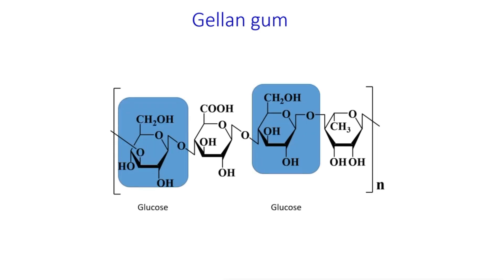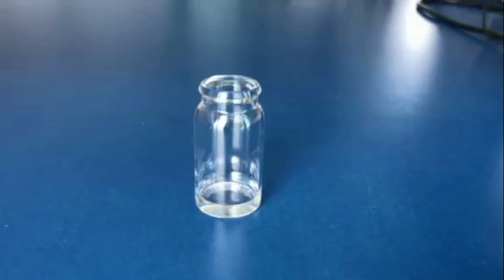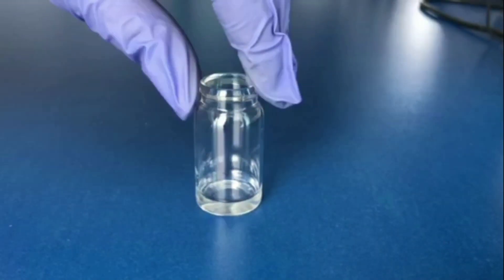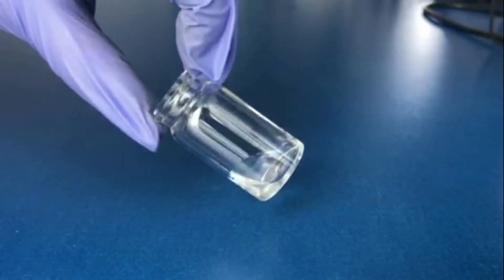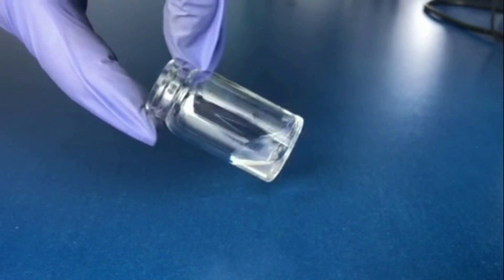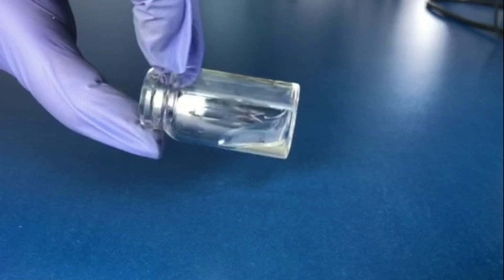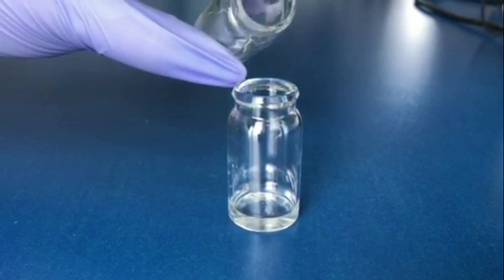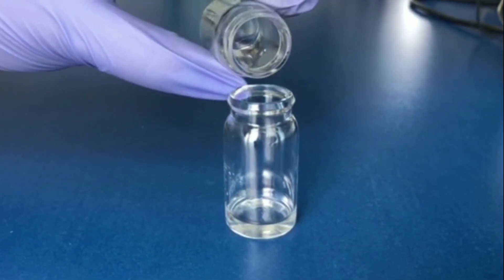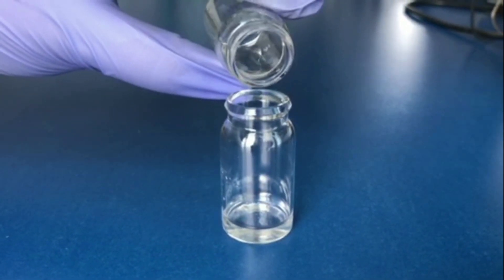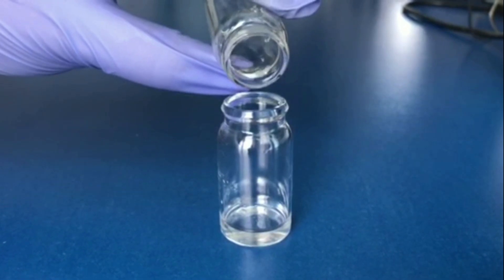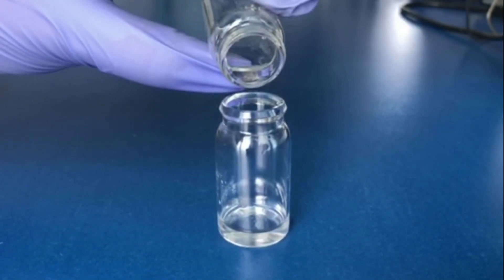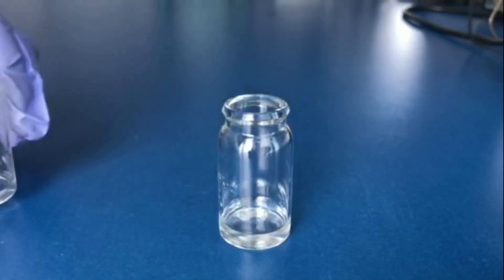of each residue of L-rhamnose and D-glucuronic acid. In water it can form viscous transparent solutions; however, when mixed with media containing inorganic salts, it results in immediate formation of a transparent gel. This in situ gelation can occur under physiological conditions present in the ocular environment. This unique ability of gellan gum has already resulted in its application as a gelling agent.